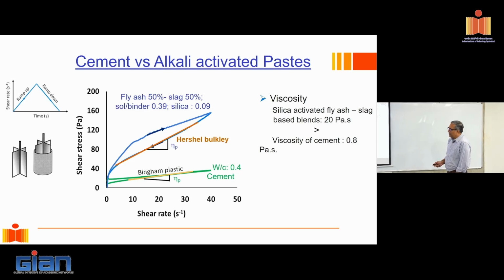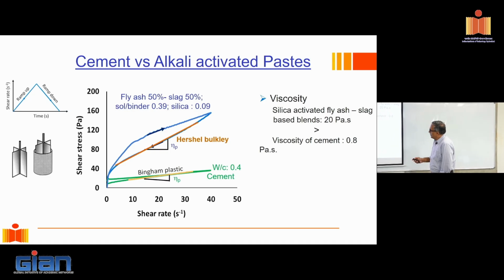It doesn't go sharply to zero at our intercept here. Instead, it tapers, and probably goes almost to a zero yield stress. This kind of behavior, which comes down here and doesn't have a sharp intercept like what you see for cement paste, is what we call Herschel-Bulkley behavior. Herschel-Bulkley is a broader term used to describe even the Bingham plastic. Bingham plastic is subsumed in the Herschel-Bulkley. Why? Because if this nonlinear portion were to become steeper, you end up with a Bingham plastic.